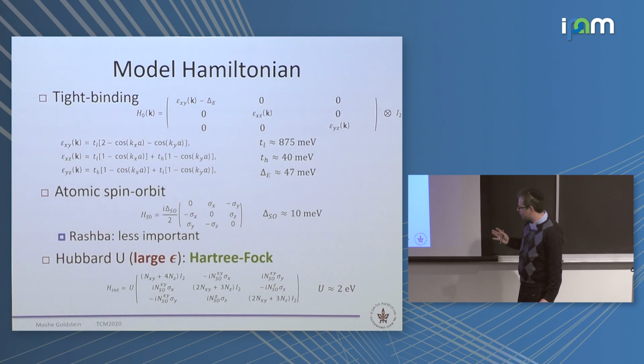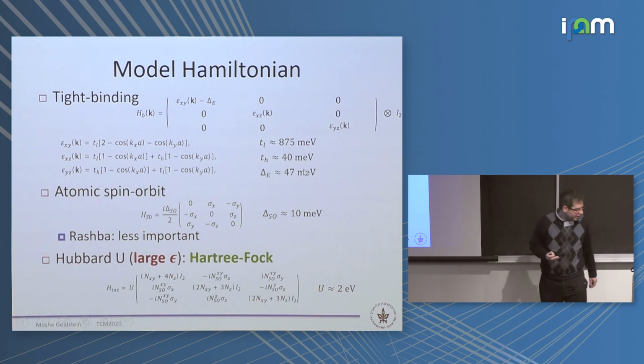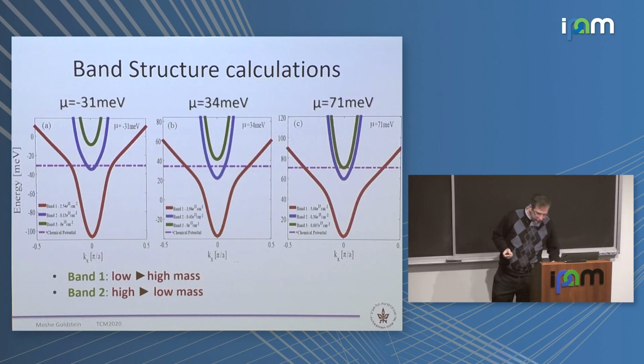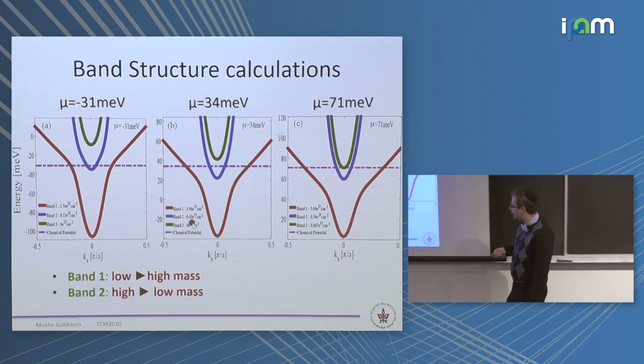And then if you use symmetry, you find that if you do Hartree-Fock, you basically have only 4 Hartree-Fock parameters, so way simpler than twisted bilayer graphene. And again, we can take all those numbers and also the Hubbard U from DFT and experiment data. We didn't want to use them as fitting parameters, otherwise you have too many parameters. We just try to take reasonable numbers from the literature. And then you take that and you look at the bands.